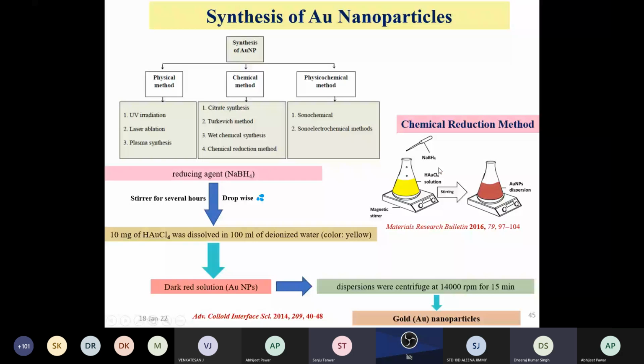The magnetic heater stirrer will be running. 10 mg of chloroauric acid was dissolved in 100 ml of deionized water, and after a certain time, 1 hour or 15 minutes, in the dispersion you will find a dark red solution. Generally the metal salt is a yellow powder, but when you dissolve it and add the reducing agent, after some time of stirring the color will change from yellow to red. So immediately you can see your HAuCl4 has been reduced to nano form. That's why we call it bottom up, because smaller atoms collect together and make the nano form. We call it nano colloid.